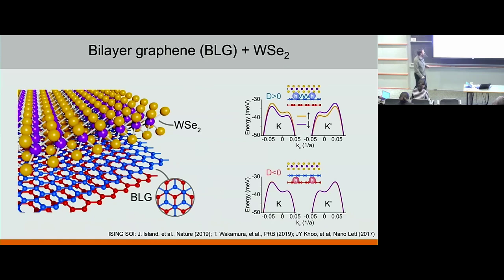The topic for today, or at least for this last session before the dinner, is bilayer graphene coupled to tungsten selenide. Even before our work, there was a lot of evidence that if you have this kind of structure and you apply an out-of-plane displacement electric field, you will induce spin-orbit coupling in this system, which will split the bands. This is a schematic representing this, where you have holes, and if you apply displacement field, such that you push these holes towards the tungsten selenide monolayer, you will have this splitting of the bands triggered by the Ising spin-orbit coupling.